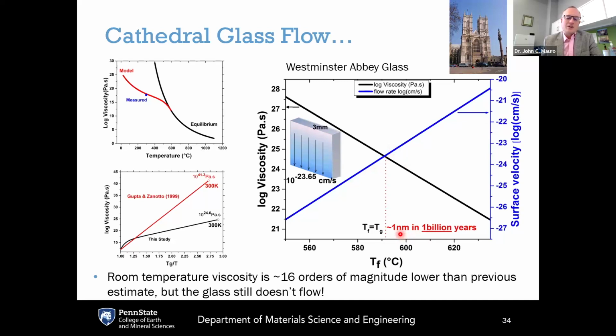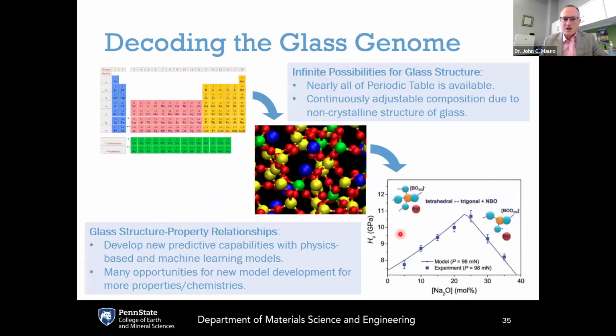So the increased thickness that is observed in some stained glass windows is not because the glass is flowing, but rather the medieval methods for making glass were based on spinning a gob of glass out into a disc and then cutting that up into little pieces. That's called the crown process. And basically that leads to some intrinsic thickness variations. And it's only natural then for the stained glass artisan to put the thicker part on the bottom because that at least gives the appearance of being more mechanically stable.